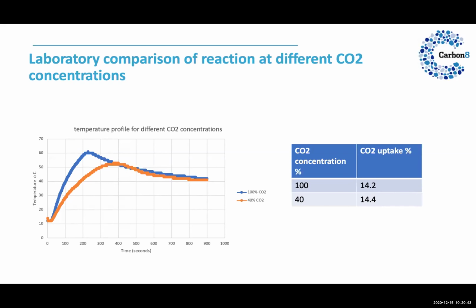But if you look at the CO2 uptake of the products of this process, there's very little difference. It's a bit artificial here in it showing that the 40% uptake is slightly higher than the 100, but that's within the experimental error of the determination. So really what it's saying is that we're not affecting the CO2 uptake as long as we're delivering sufficient CO2. And in the commercial plant, that's the balance that you have to make between the flow rate of the CO2 and the problem that you might blow all the fine dust that you're trying to treat out of the mixer. So it's the materials handling side of the process that is the key to the success.